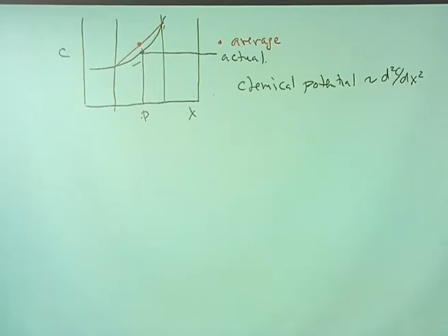And so if the interaction distance was in fact 0, like you have in the nearest neighbor model that we just did, this effect wouldn't appear. But in real systems, the long-range interactions exist, and so you have this coupling between the curvature and the actual value of the chemical potential at P. Okay? And so the system is surrounded in this case by more atoms that it dislikes than it would be at equilibrium. And so what that means is that the free energy